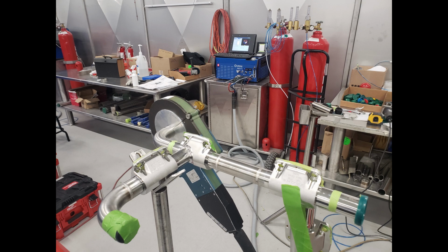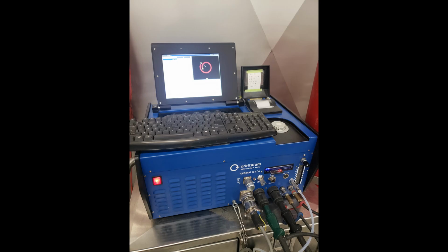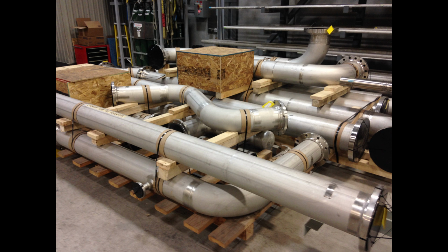Stainless tubing: no shrink. In fact, it shrinks a little bit, but you can ignore this shrinkage. So you don't have to consider shrinkage when calculating pipe cut size. Nowadays, it is mostly welded by an orbital welding machine. Schedule stainless pipe such as Schedule 10 or Schedule 40.